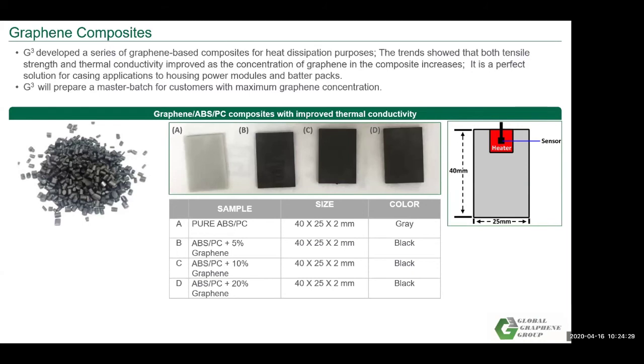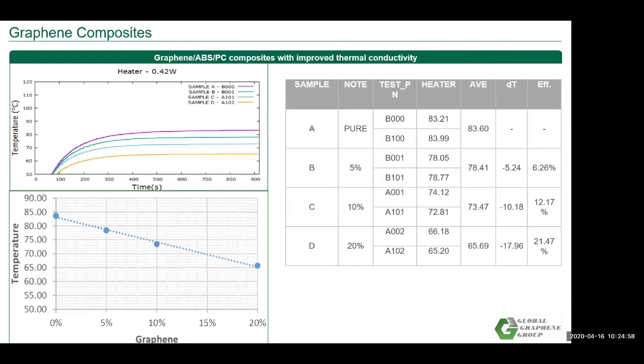We also put graphene into many polymer materials to make graphene composites. So this is an example where we put graphene into our ABS PC composite at different percentages of graphene content, and we investigated how effective it is at dissipating heat. As you can see in this slide, with a higher percentage of graphene, the thermal dissipation improves, and we can reduce temperature from 85 degrees C all the way to 65 degrees C. So that's about 20 degrees C difference. This shows graphene is very effective in composite form.